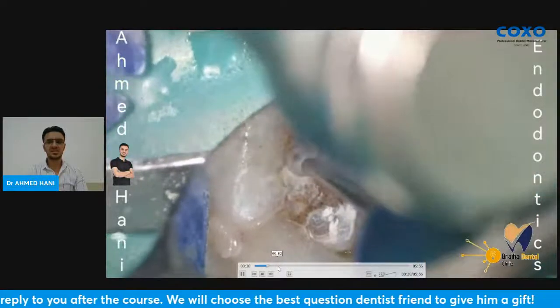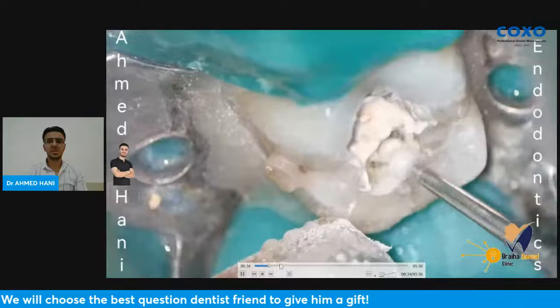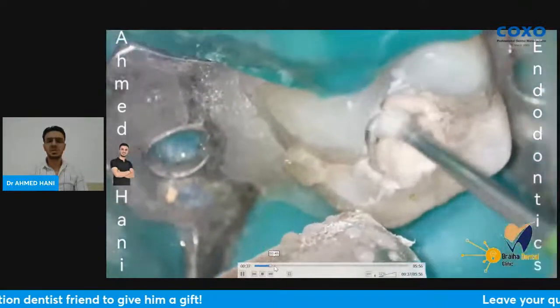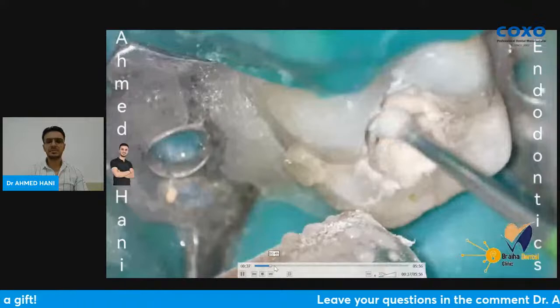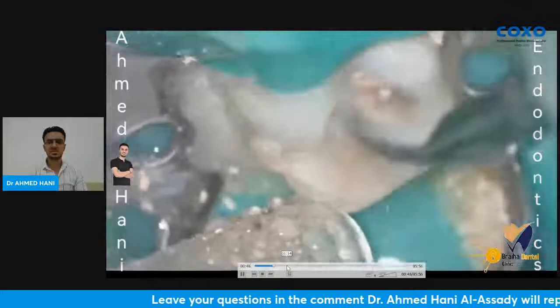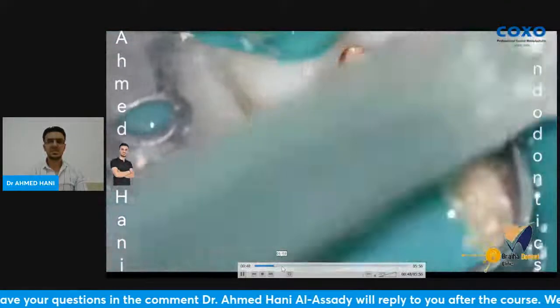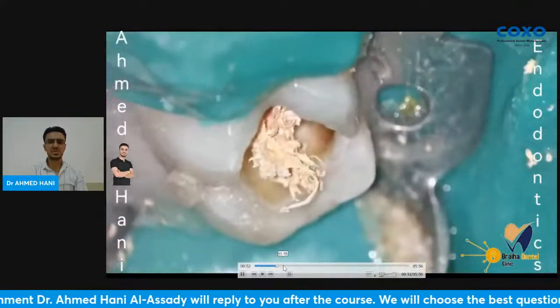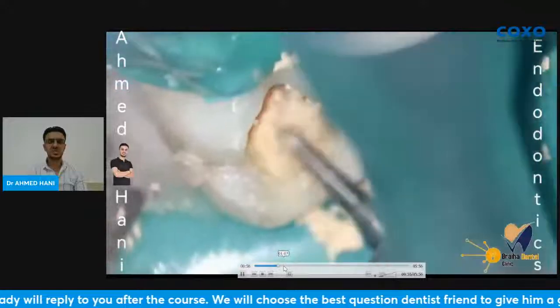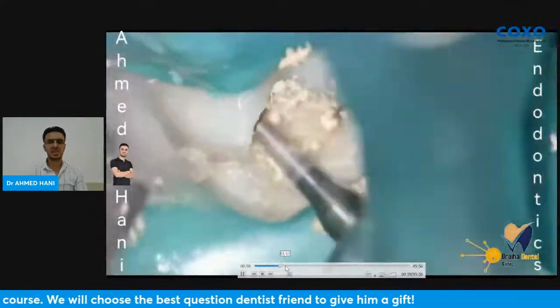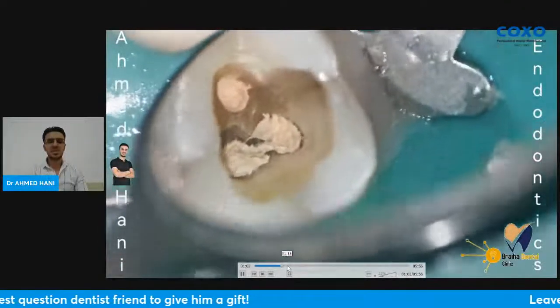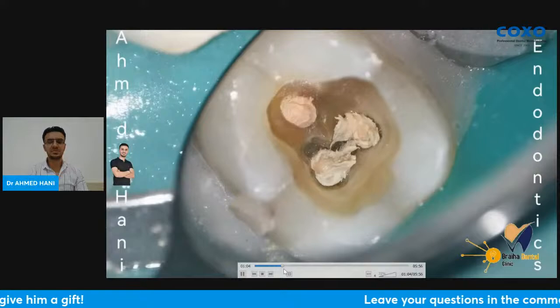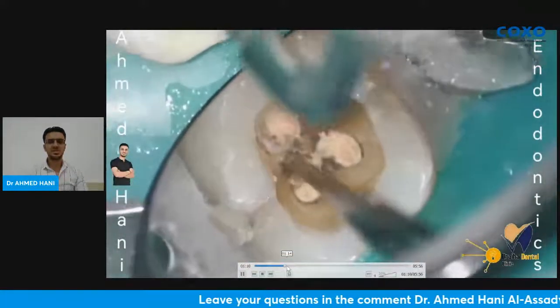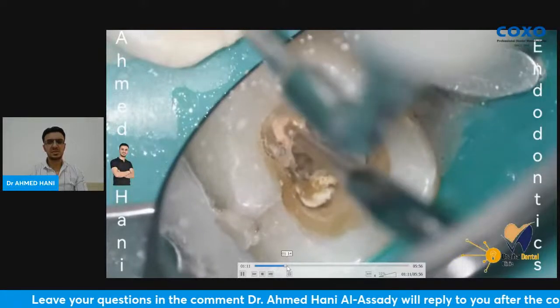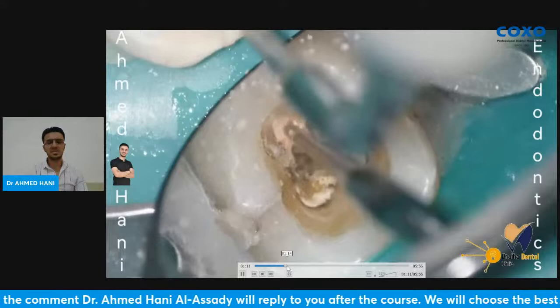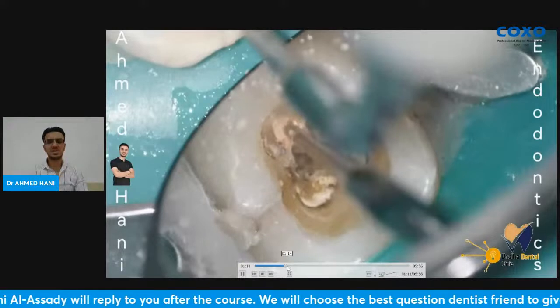Then fill the canals with a single cone and calcium silicate based sealers, which were recently launched into the market in the last 3 to 4 years. This technique depends on the properties of the bioceramic, calcium silicate based sealers: alkaline pH, bactericidal, expand when set, zero shrinkage. All these properties allow us to obturate three-dimensionally using calcium silicate materials with just a single cone.